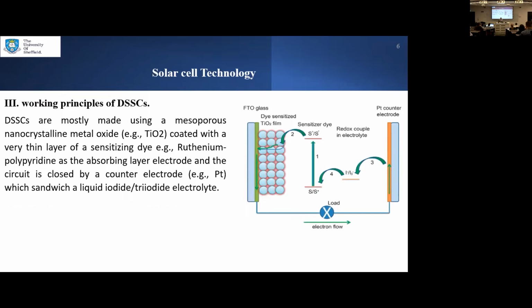Well, here, this one is also a dye-sensitized solar cell. It's also known as the excitonic method of generating electricity. And this actually uses mesoporous nanoparticles made of titanium oxide, which is being coated using ruthenium polypyridine, to create where you have your electrons here. And when they absorb photon energy, the electron within them tries to escape to generate electricity. And electrolytes made of iodine try to refill the nanoparticles there.